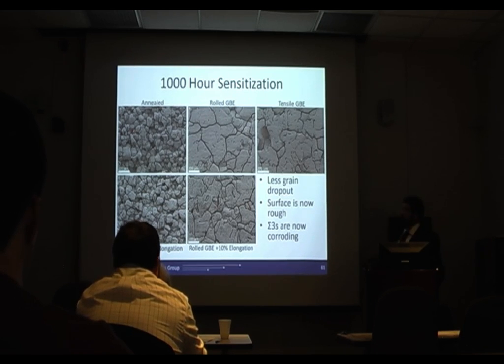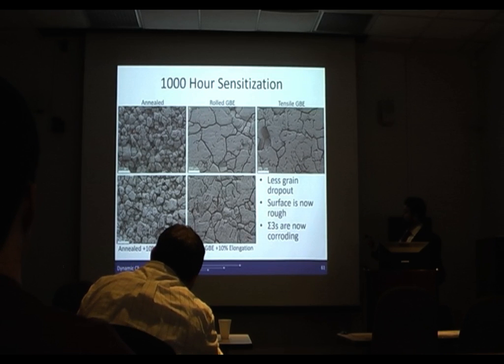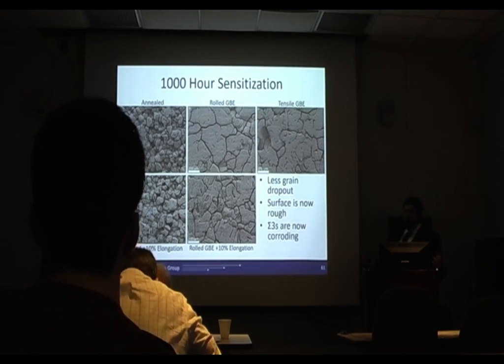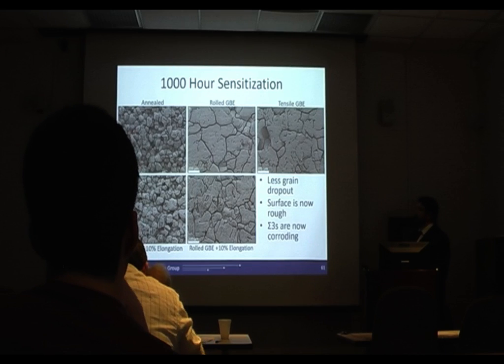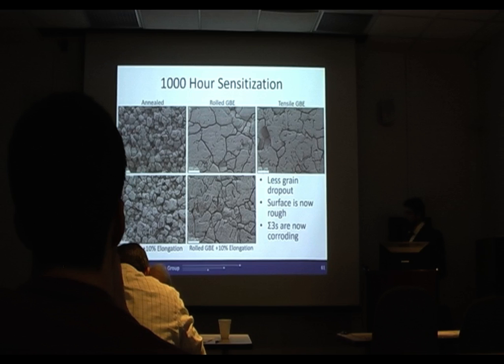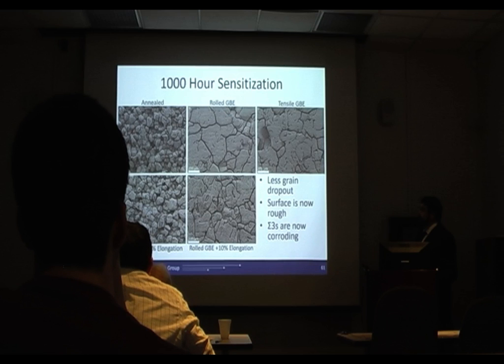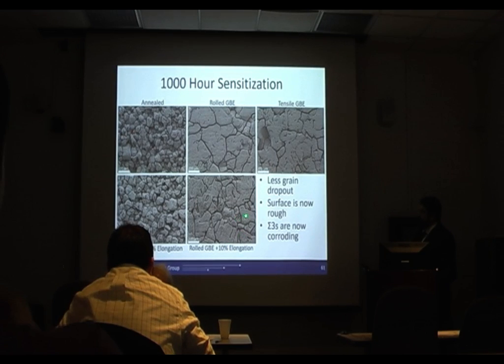It undergoes a little bit of attack, but in the 1000 hour, we actually have this very rough surface texture. And for the most part, except for the tensile GBE, our mass loss went down, but we have that change indicating that something different is happening in those at this sensitization time. And this is especially noticeable in the added strain conditions, because you can see these parallel lines in some of the grains, and those appear to be the coherent annealing twins. And once we add strain and go to the very long sensitization, they're actually now being attacked, which has not been previously observed.